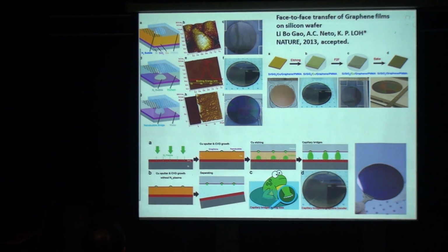We first have this silicon oxide. Normally, this is what we do. We use a nitrogen plasma to engineer trapped gas within, and then we sputter the copper, which is the catalyst, and then we grow the graphene on the copper. And by some treatment, the bubbles start to appear from the substrate, and then these bubbles will merge to form a capillary bridge, so that when the etchant solution comes in, it removes the copper catalyst.